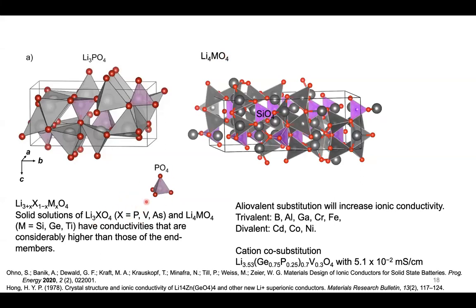the polyanion can really take place in a number of ways. So this X can be phosphorus, which is the phosphate that you've seen, vanadium, even arsenic, the typical elements for M here in the Li4MO4 parent phase. M can be silicon, germanium, titanium. And so that's what people have done.